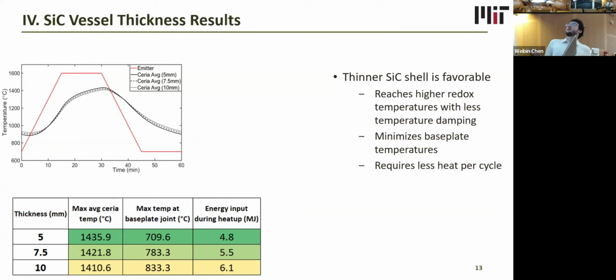We can also see that the thicker silicon carbide results in higher temperatures at the base plate joint because it's conducting more heat down to the base plate, which is not desirable. And it also uses more energy input to heat that big hunk of silicon carbide.